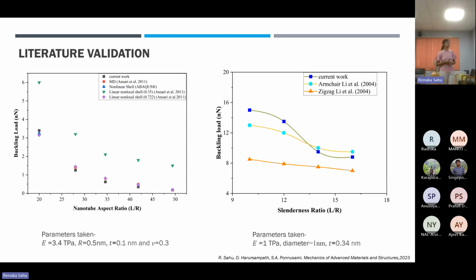We can see that the current work gives very good correlation with the non-local shell model for the 0.722 non-local parameter, and also with the molecular dynamics result which was already used in the paper itself. As we can see, with increasing nanotube aspect ratio, the buckling load is decreasing.